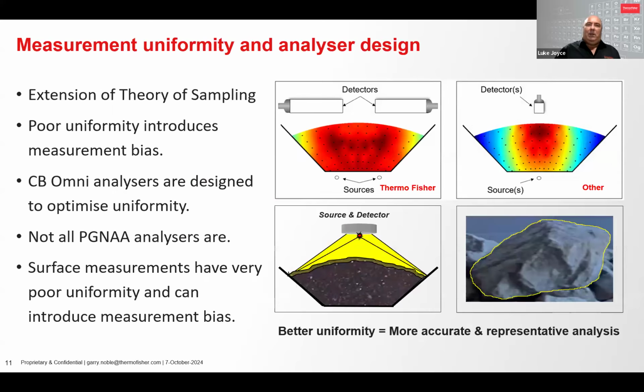So measurement technique alone does not ensure a solution that works. Unlike laboratory analyzers where samples are prepared and presented to the instrument in a consistent and uniform manner, online measurements must be designed to perform under varying material flow conditions. To achieve a representative laboratory analysis, the first step is to take a representative sample based on theory of sampling, which requires that every particle in the stream has an equal probability of being included in the sample.